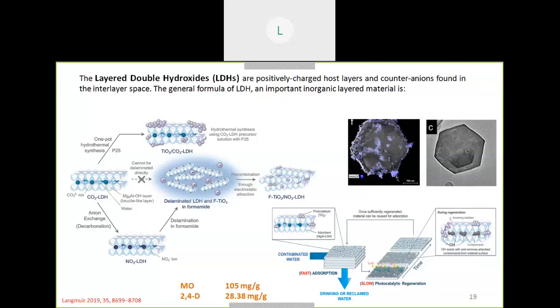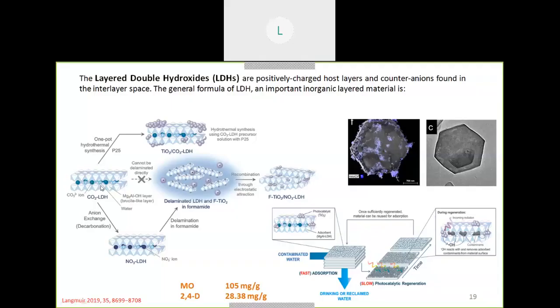So they exchanged the carbonate ion with nitrate first, because carbonate has high hydrogen bonding attraction between the layers, so the layers would again reconstitute. So they interchanged with nitrate ions, and intercalated the TiO2 by putting the TiO2 in formamide solvent. After putting the TiO2 and the LDH together, they get this structure of LDH and TiO2.